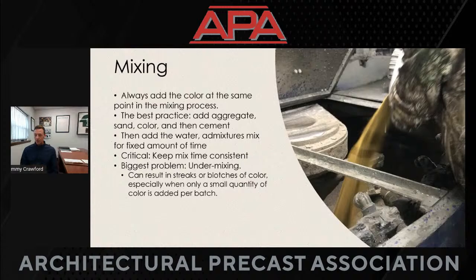I have a question here. Related consistency question from email. Occasionally, we have a hard time controlling the consistency of our light buffs. Any thoughts on how to improve consistency? Absolutely. I have a few thoughts. One, my question would be, what is the formulation of the buff? If you're making buff using a red, yellow, and black synthetic iron oxide blend, you're going to have more difficulty controlling for color than if you use a natural iron oxide. Why is that? You start with red, yellow, black synthetic versus starting with a buff pigment.